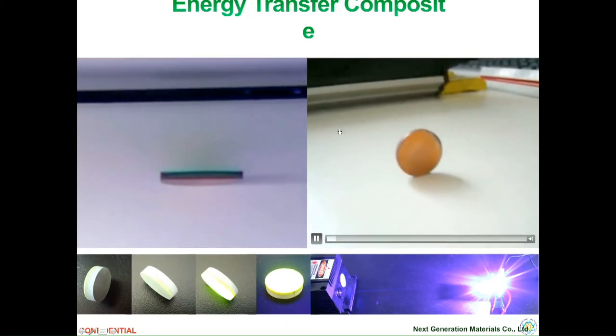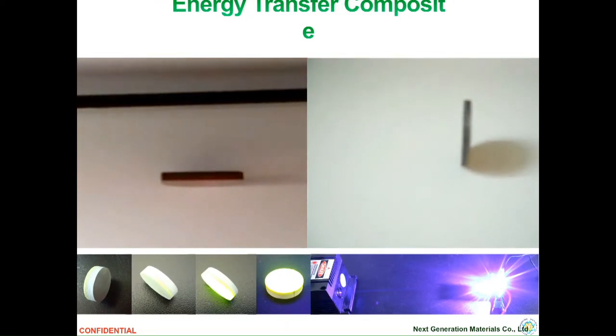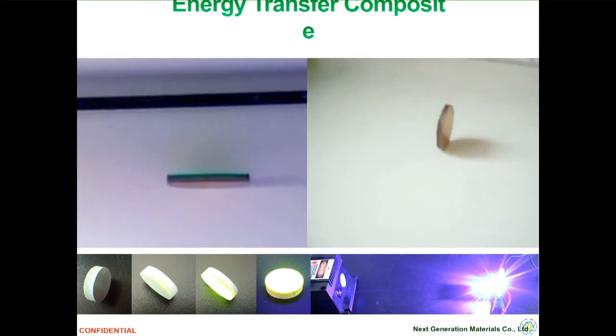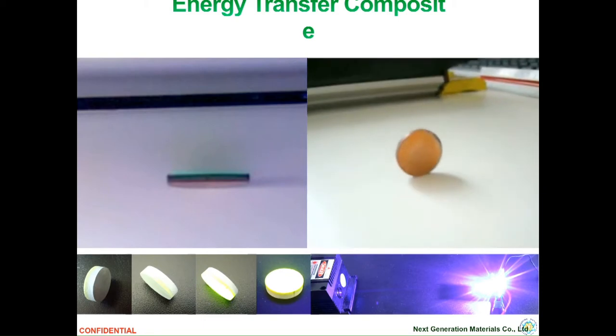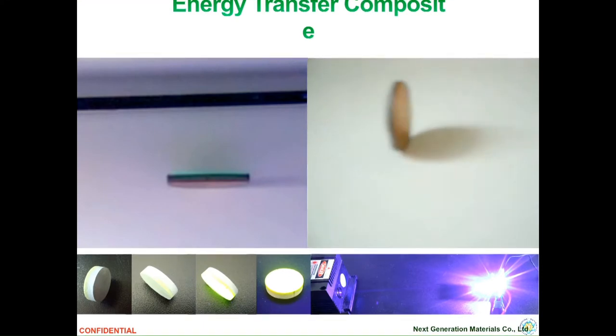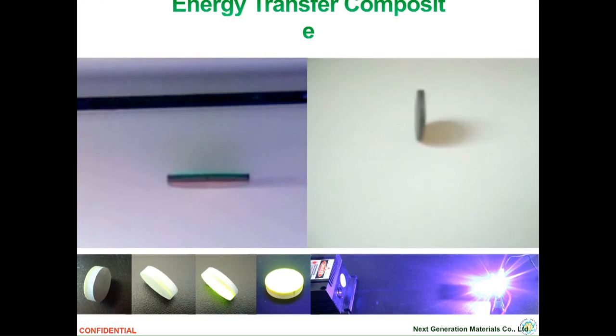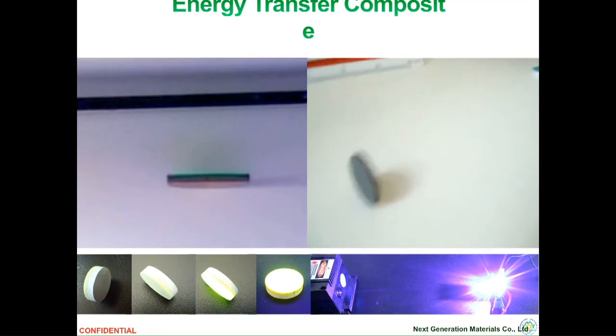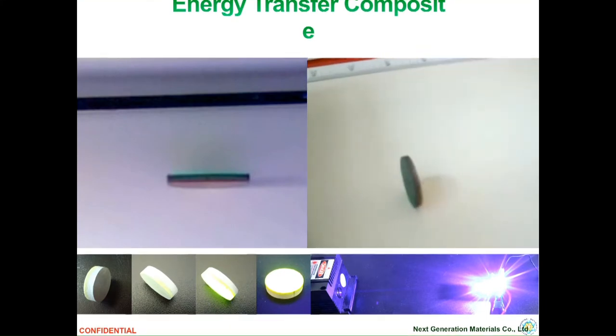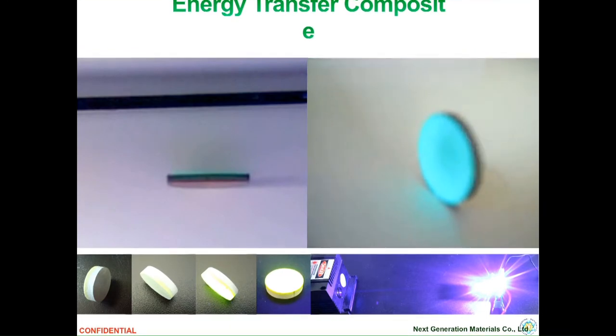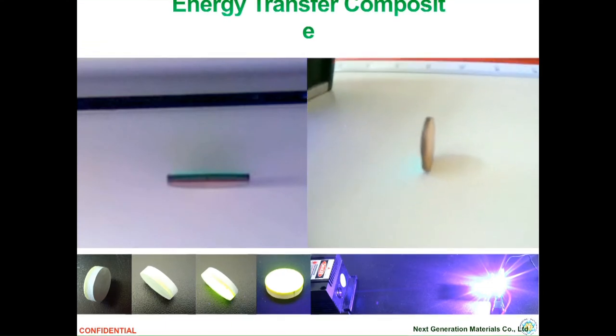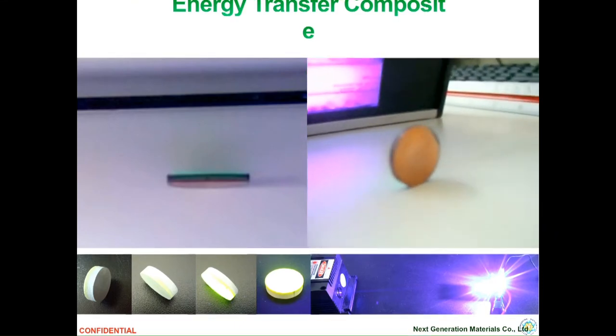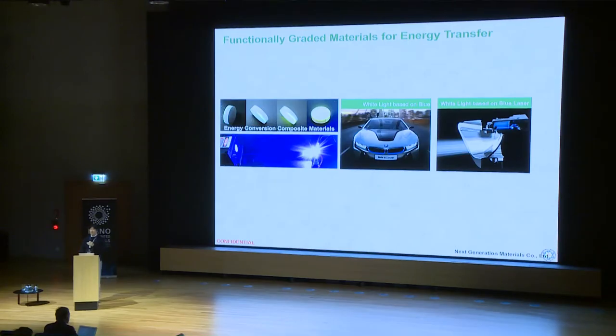When I turn on the 365 nm UV light, you can see the green light turning on. The left shows just the ceramic part, and the right short movie shows: the front layer is ceramic and behind it is copper. Each layer is combined with single-wall carbon nanotube. When I turn on the 365 nanometer UV light it emits visible light. This means we can use this material as a sensing material, and also for a very interesting laser light application.